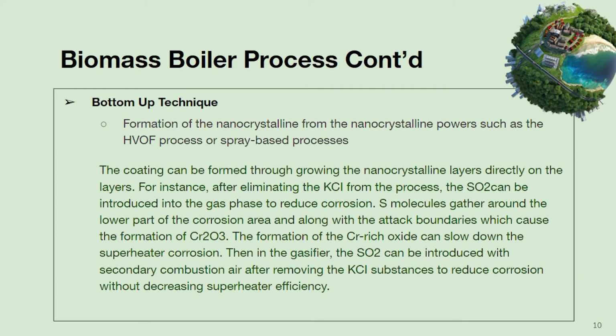The formation of chromium-rich oxides can slow down the superheater corrosion. Then, in the gasifier, the sulfur dioxide can be introduced with secondary combustion air after removing the potassium chloride substances in order to reduce the corrosion without decreasing the efficiency of the superheater.